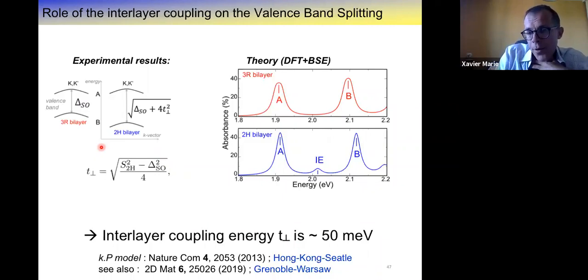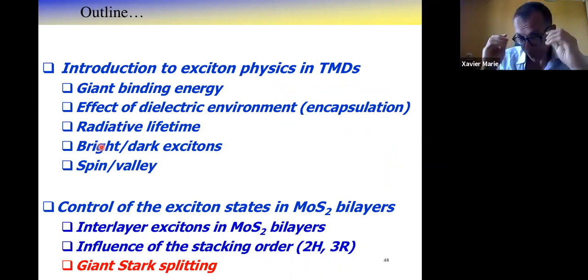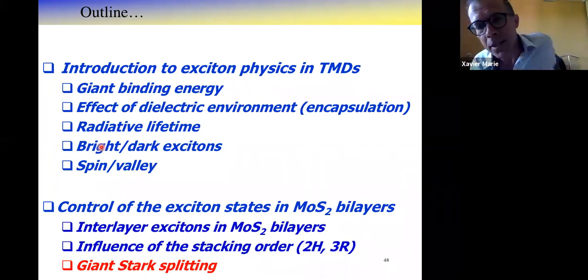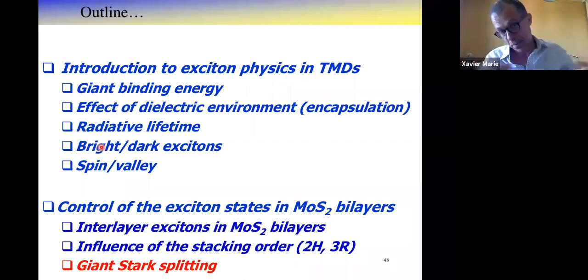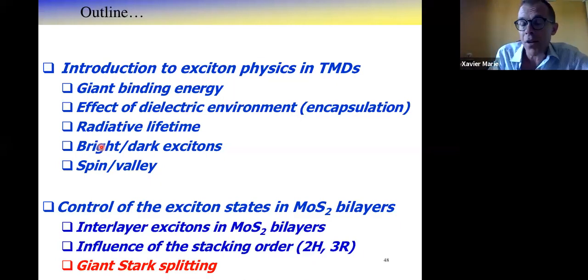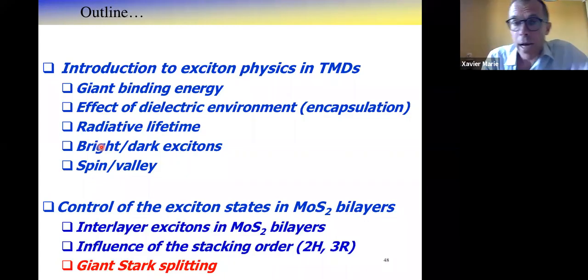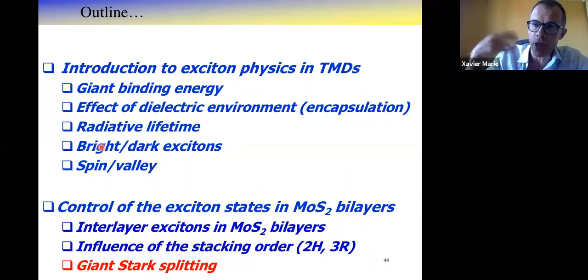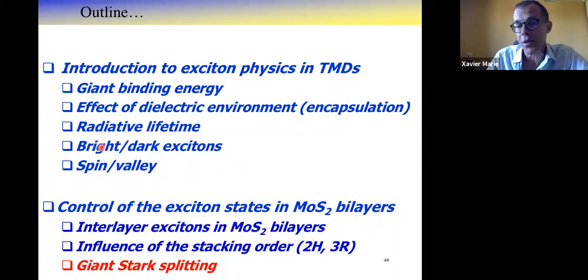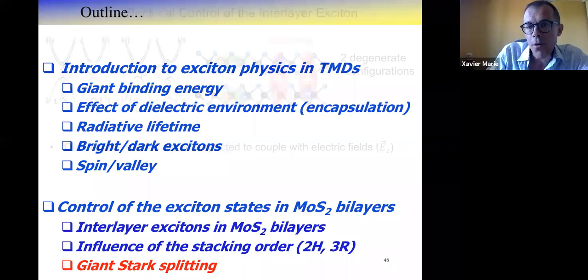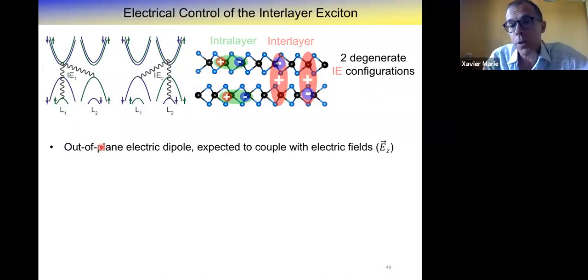So just to finish now, once we have evidence of this interlayer exciton, what we would like is to play with it and to control this interlayer exciton. Because though in monolayers the excitons have fantastic properties, one of the disadvantages is that you cannot control them easily with electric field because they don't have an out-of-plane dipole. It's really a 2D exciton. So for many experiments we'd like to perform, to study exciton-exciton interaction, strong coupling, exciton polaritons, it would be nice to have a way to control this exciton, for instance, with an electric field. With a monolayer, it does not work, but with a heterobilayer it has been shown, and here with this homobilayer, I will show you that again, we have a very nice way to tune the interlayer exciton state just with electric field. How does it work?